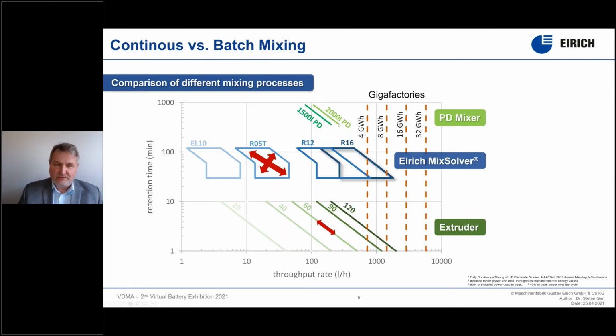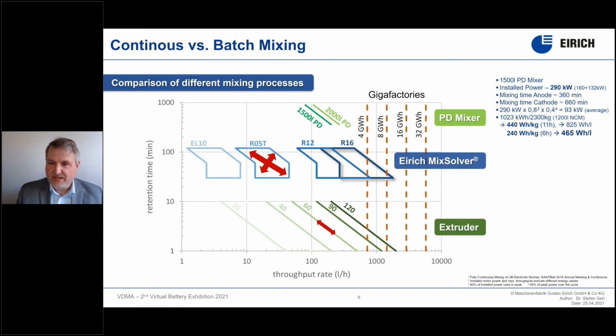Why? You see, with the PD mixers, you have to adapt or use a huge number of machines in parallel to allow the production rate of a gigafactory. If we compare the energy consumption, it's quite interesting to see. If you have a 1,500 liter PD mixer, which is a filling of about 1,200 liter, they have installed power in total of 290 kilowatt, 160 kilowatt for the solver tool, and 132 kilowatt for the planetary tool.